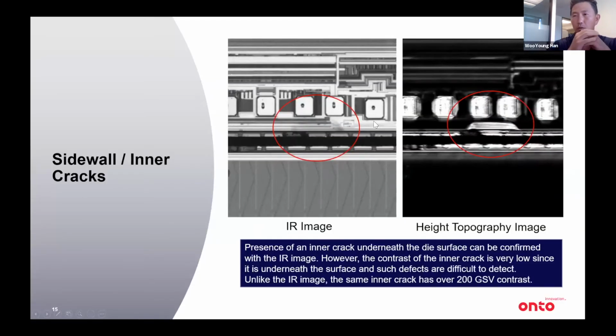And here's another example of a sidewall or inner crack. In this case, even the IR camera had a hard time seeing the crack underneath the die surface. If you look at the image on the left side, that's the infrared image, and you can see a very faint signature of the crack underneath the die surface, right? With contrast as low as that, it'll be difficult, pretty much impossible, for any algorithm to find that kind of contrast and look at it as a defect.